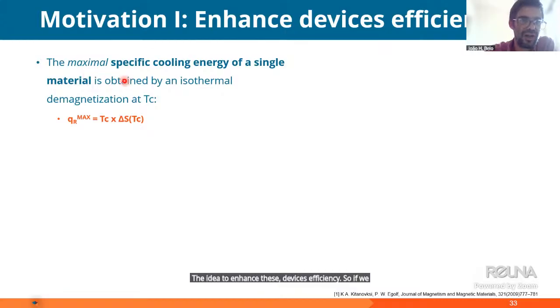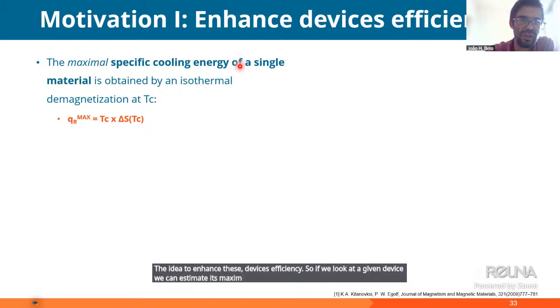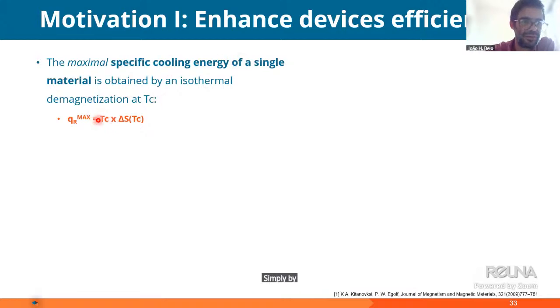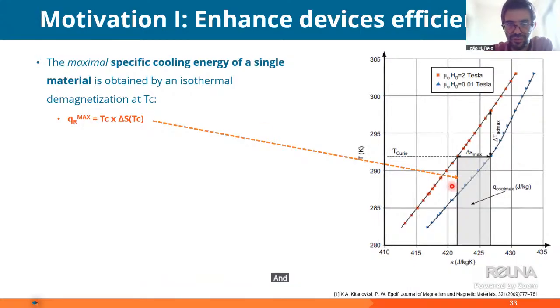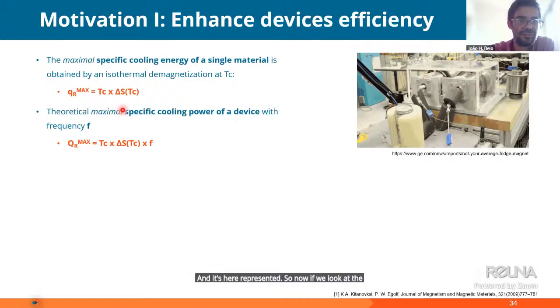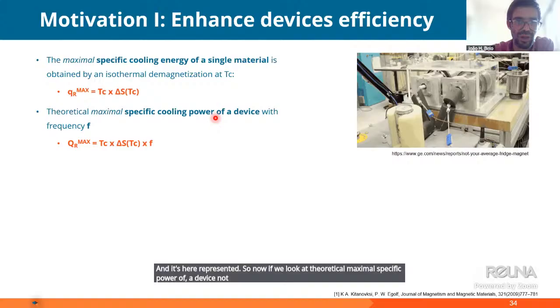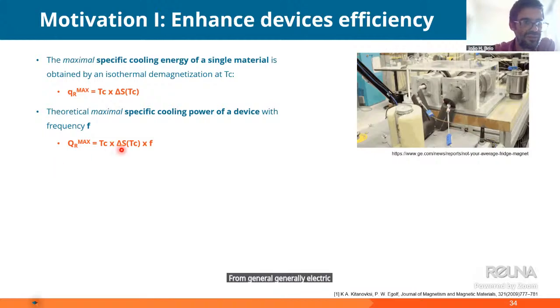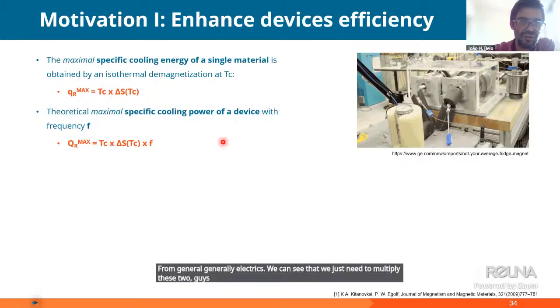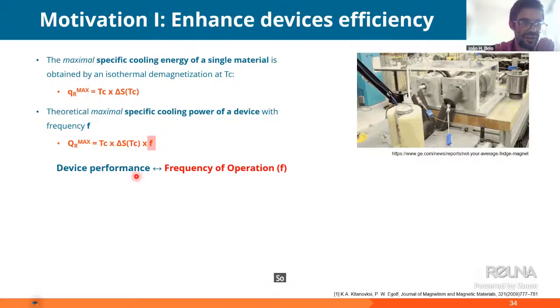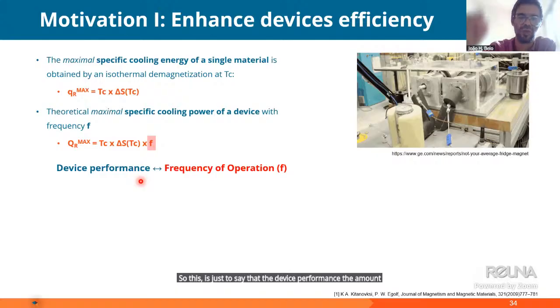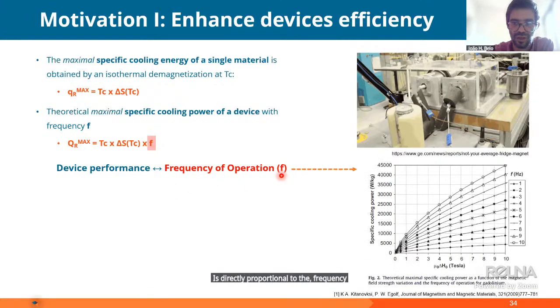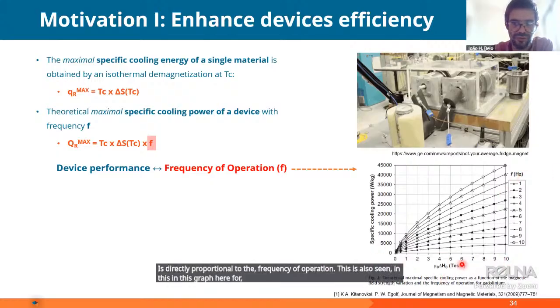So if we look at a given device, we can estimate its maximal specific cooling energy simply by multiplying the TC by the delta S at TC. So this is what we call the maximum specific cooling energy of a single material. Now if we look at the theoretical maximal specific cooling power of a device, not a material anymore, here you can see a prototype example from General Electric, we just need to multiply these two again times the frequency of operation of our device. So the device performance, the amount of heat being transferred, is directly proportional to the frequency of operation. This is also seen in this graph here for different applied fields.